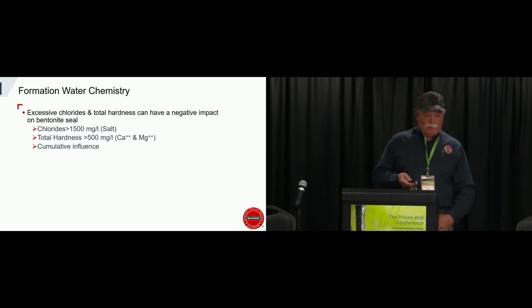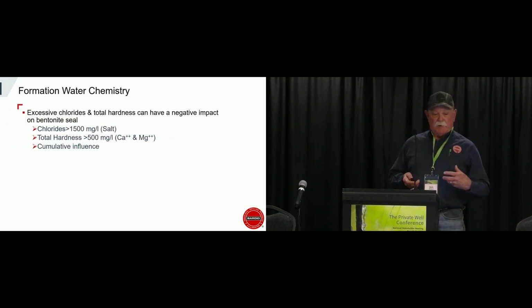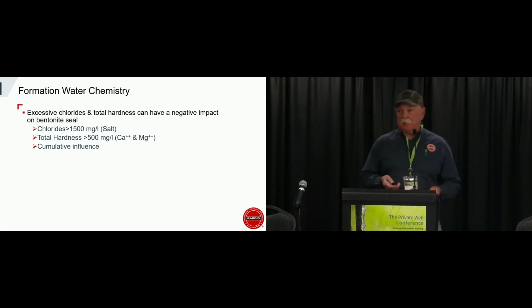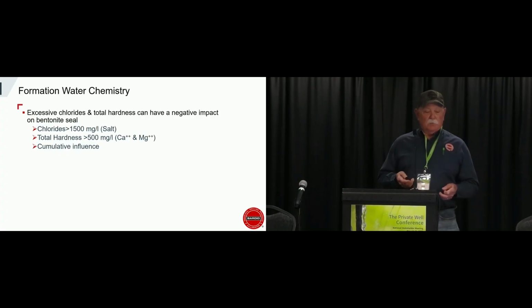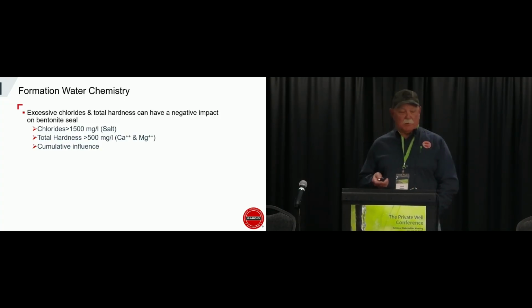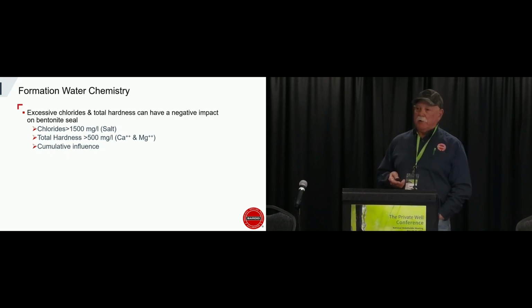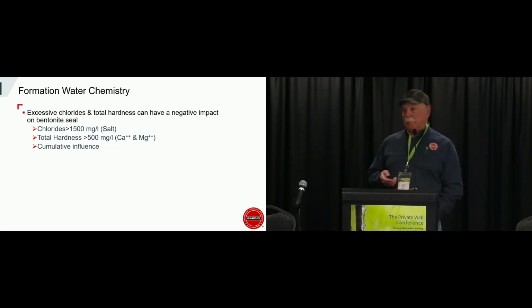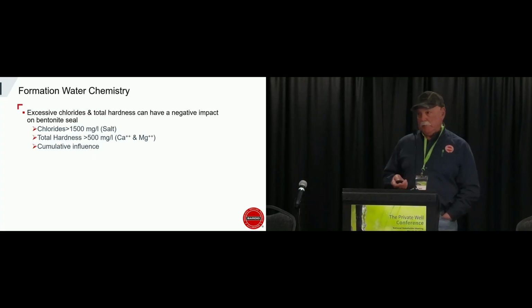Formation water chemistry. Excessive chlorides and total hardness can have a negative impact on a bentonite seal. Chlorides in excess of 1,500 ppm, which is basically salt. Total hardness of 500 ppm or milligrams per liter with combined calcium and magnesium. And having these both is a cumulative effect. I was working on a job down in Dixie Valley, Nevada, and that definitely wouldn't be good for bentonite. The chlorides were about 25,000 parts per million, and the total hardness was over 2,000. But in that case, we use cement.